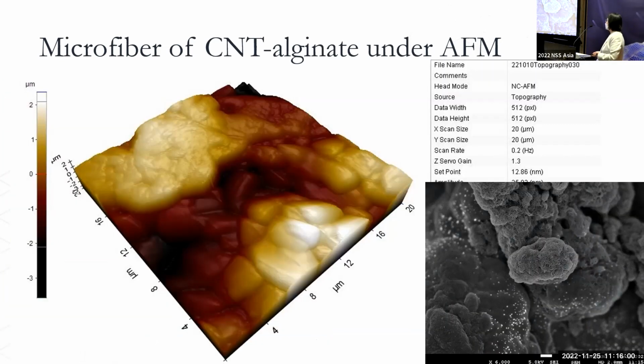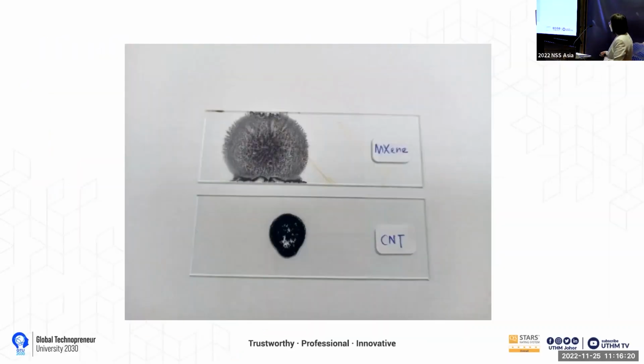Right, so this is a carbon nanotube alginate under the AFM. So the fiber was produced using the wet spinning technique. Right, so let's see how the carbon nanotube alginate looks like. So you can't see the carbon nanotube actually because you have encapsulated it with the alginate. So it's all covered up. This is how it looks like. But we can show you the carbon nanotubes. This is how it looks. The carbon nanotubes are in the bigger particles.